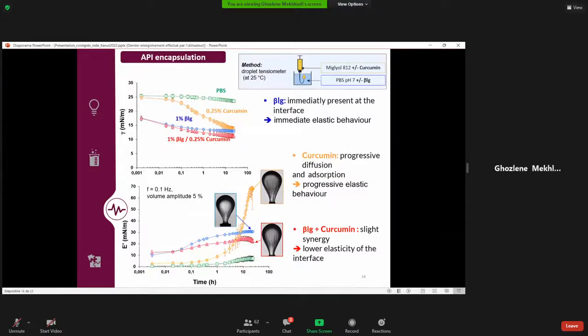On the other hand, we followed the time evolution of the interfacial tension here, and also the elastic modulus. And we saw for the system composed of the protein alone, as expected, there is a rapid decrease of the interfacial tension, and thus the protein is immediately adsorbed at the interface, and there is an immediate elastic behavior. Whereas when we have the system with curcumin alone, curcumin diffuses and adsorbs progressively to the interface, and the elastic behavior appears gradually. And for the last system composed of both molecules, we see that there is a slight synergy as the elastic behavior is more pronounced.